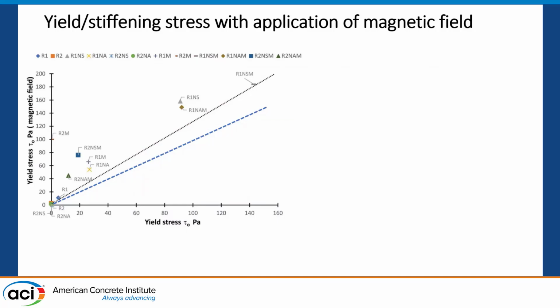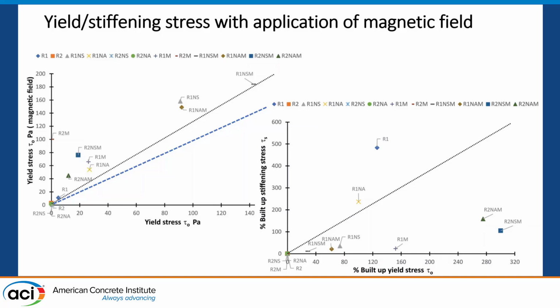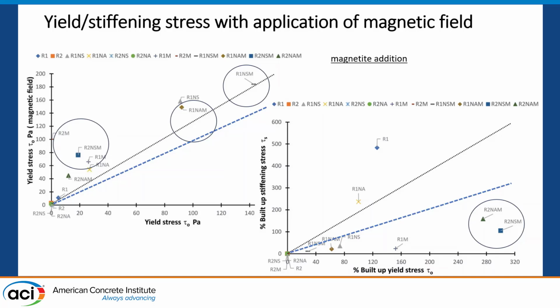To summarize the effects, I can compare yield stress of the material without field and when we apply a magnetic field, and you can see that enhancement of the yield was demonstrated for all the materials we tested. Another important point is that in some cases the stiffening stress was also enhanced for some compositions. Specifically, the magnetite addition was very beneficial to achieve the top levels of performance of the investigated systems. Again, magnetite is not a nanoparticle, but it is smaller than 1 micron, so sub-micron particles, and they were also providing a very unique response.